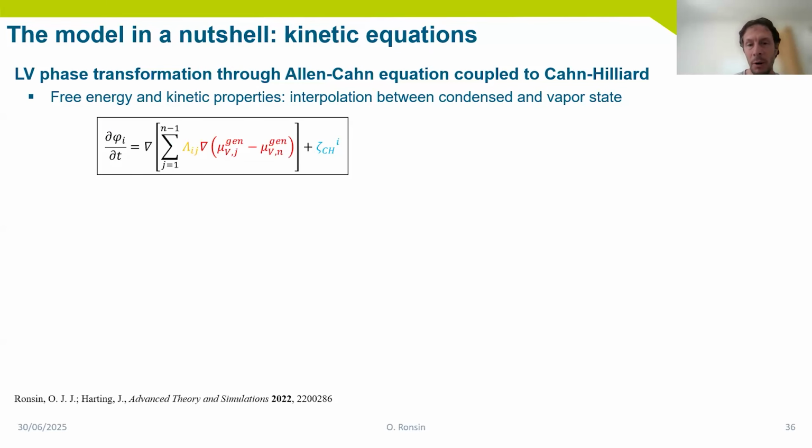And now, how do we trigger evaporation? We just extract solvents from the box with a boundary condition at the top of the box, which looks like the equation here. And without going into much detail, this equation corresponds to the Hertz-Knudsen theory of evaporation rate, which has proven to be nicely representing experimental results, even if not fully perfect.